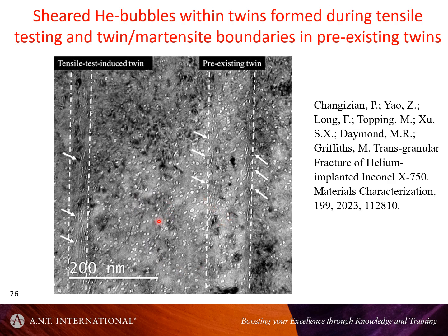using this absorption contrast mode where you're looking for the contrast from the cavities and not the contrast from the structure, the twin or whatever it is that you're looking at, some complex structure. And what he saw was that clearly here you had some shearing going on. And again, you can argue that, well, maybe that's twinning or maybe it's dislocations. But one of the arguments for dislocations is that there's such a high strain, there's such a very large shearing going on here that it can't be a twin operation.